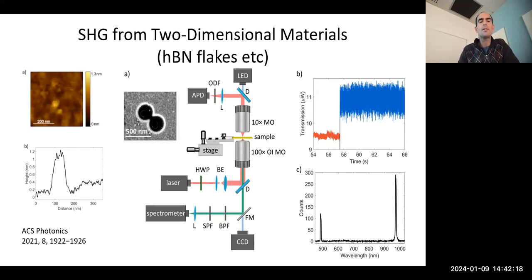So we looked at these flakes of hexagonal boron nitride. These are 2-dimensional materials - literally about 50 nanometers across, with thickness below a nanometer per layer. We trapped these in our optical tweezer system, and surprisingly, you see a lot of signal when you trap them.